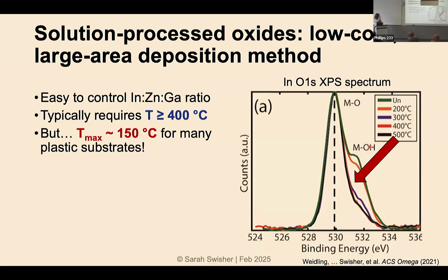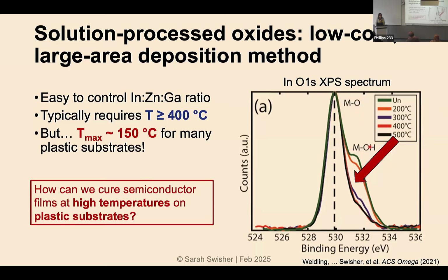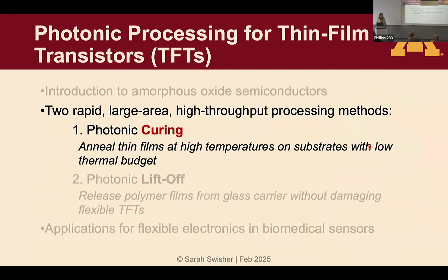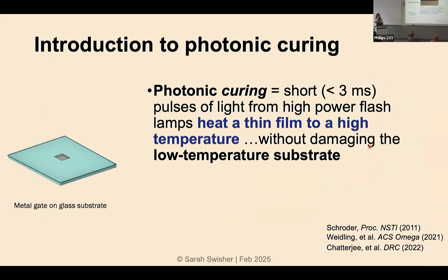And the problem here is that the maximum temperature for a lot of plastic substrates is about 150 degrees, if you want to go with something like polyethylene terephthalate, PET, which is really cheap and really common. So then the question is, how can we cure a semiconductor film at really high temperature on a plastic substrate that doesn't want to go above 150 degrees? Okay, so that's where this photonic curing comes in. So again, these are two separate methods. I'll talk about the photonic curing first.